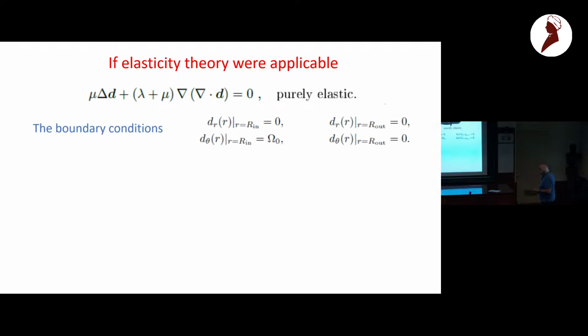So if elasticity theory were applicable, what you need to solve is a well-known equation that you can find in Landau and Lifshitz for the displacement field. So mu is the shear modulus, the Laplacian of D, lambda plus mu, the two other moduli, the Lamé moduli, the gradient of the divergence of D equals 0. And this, with the boundary conditions that we now have: the radial component is 0 at R in, whereas the angular component is not 0 because we are rotating there. And at the outer ring, they are both 0.